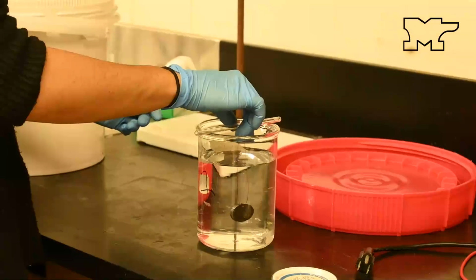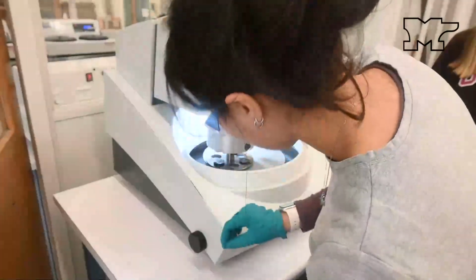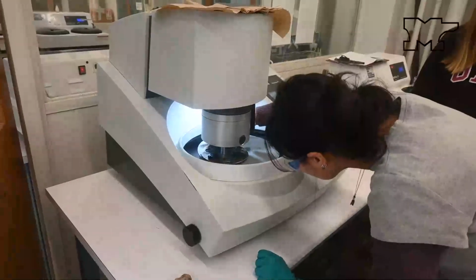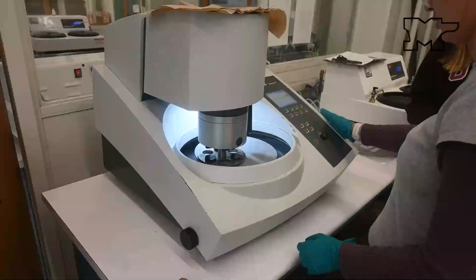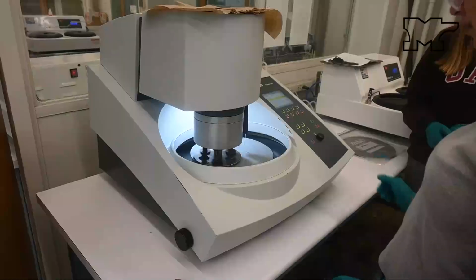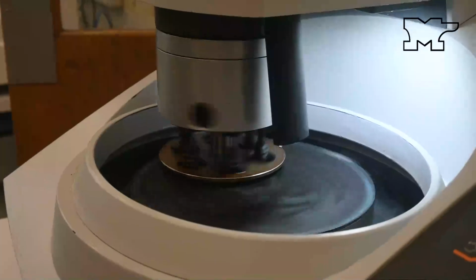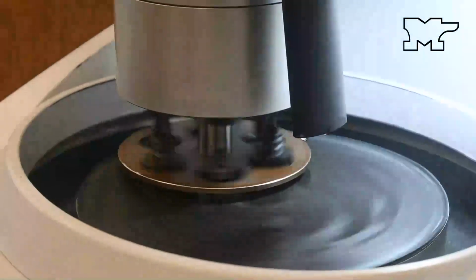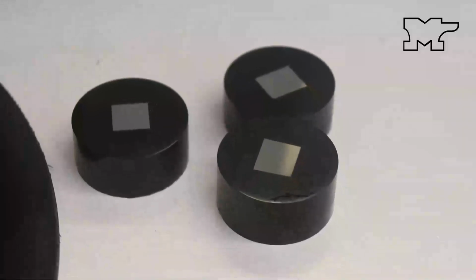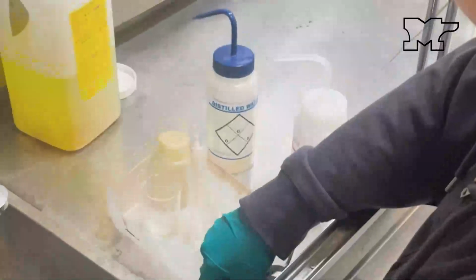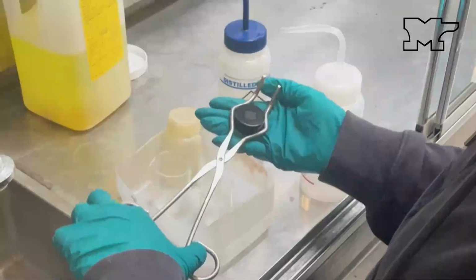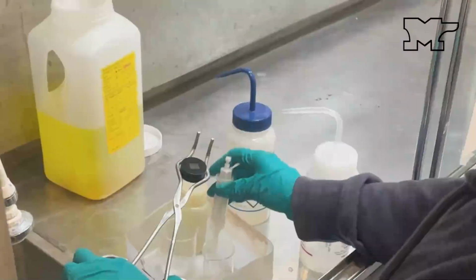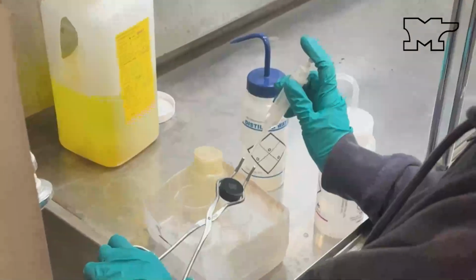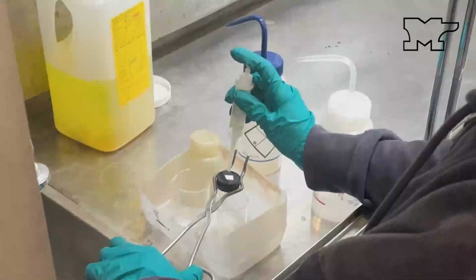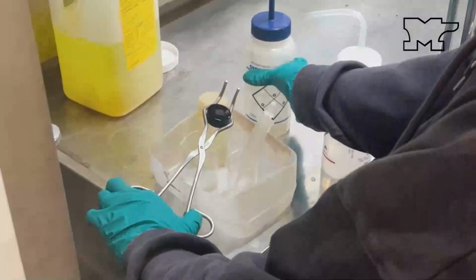After testing was complete, cross-sections were taken from the heat-treated Charpy impact samples and hot mounted. They were subsequently ground and polished using an auto polisher down to 1 micrometer diamond suspension to achieve a mirror finish. After polishing, the samples were cleaned with ethanol and then etched using a 2% nital etchant in a fume hood with secondary containment. We found a significant variation in etching speed between our samples and could thus conclude that they exhibited a large variety of microstructures.